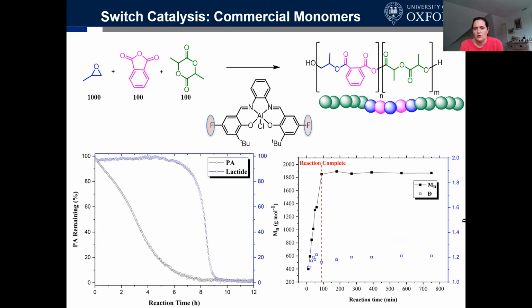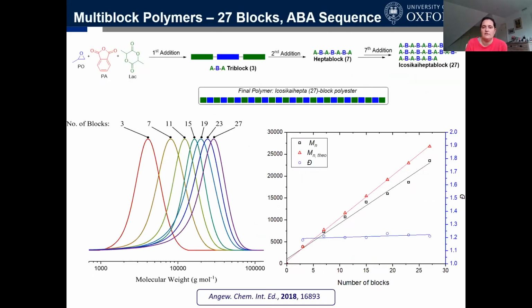We can also show that when we have the right catalyst, even though we're making a block polyester, and I'm using green to show you the PLA and blue-pink to show you the alternating polymer you make from epoxide anhydride, even though we're making a complete polyester backbone, there's no transesterification. So when we look at the molecular weight and dispersity profile of our polymer long after reaction is complete, over more than 8 half-lives of reaction, we don't have any change in dispersity. There's no transesterification.